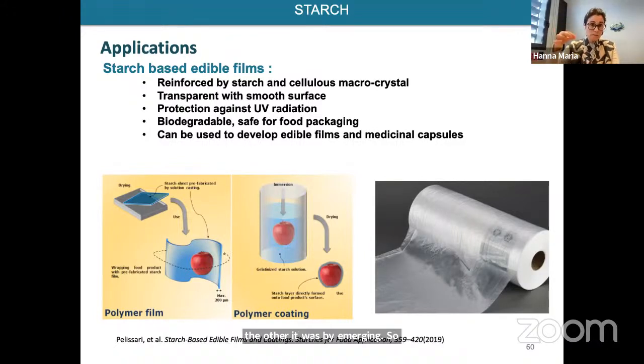So we make the solution of starch, and then we put our apple inside, and then again the solvent, the water, was evaporated. And we have a coat on the apple, and this was, for instance, to increase the conservation time of the fruits. And it was working. It was really very nice. And we did the same thing, but putting some chitin nanocrystals inside. And what was amazing, with the chitin nanocrystals inside, we observed that we were able to conserve the fruit for more time.